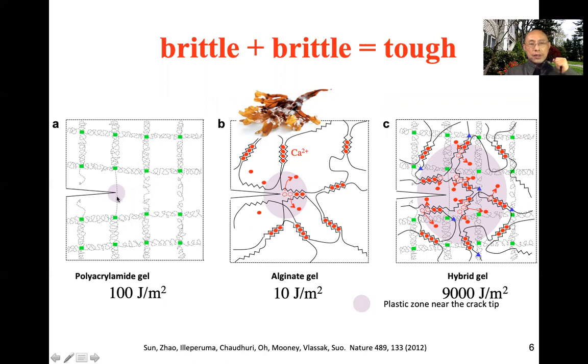Polyacrylamide gel is an elastic gel. So it has, before this chain is broken, when a crack comes in, the whole chain is stretched to covalent strength. When this bond breaks, you release the energy of the entire chain like that. So in this case, polyacrylamide gel, we measured the toughness is about 100 joule per meter squared.